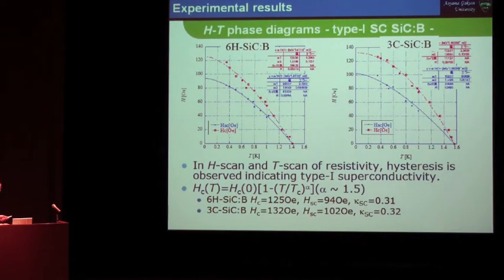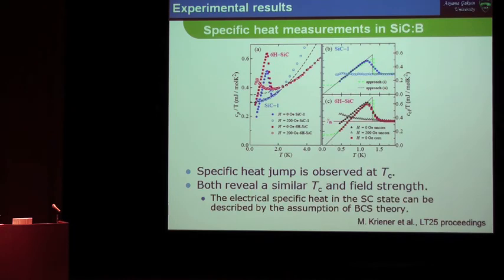This is an H-T phase diagram of type-I boron-doped silicon carbide. This is a specific heat measurement in boron-doped silicon carbide, and the specific heat jump is observed at TC. Both reveal a similar TC and field strength, and this shows the bulk nature of these superconductors.